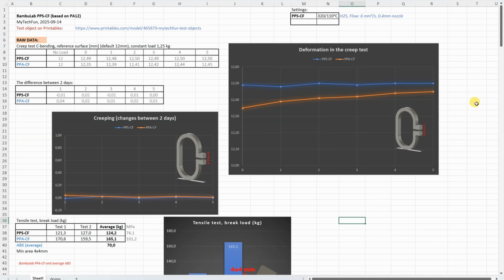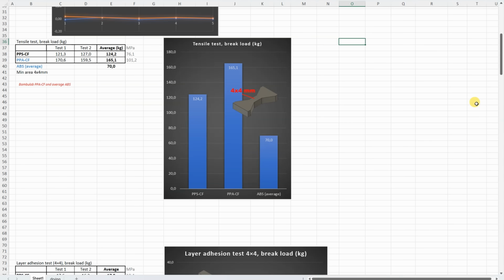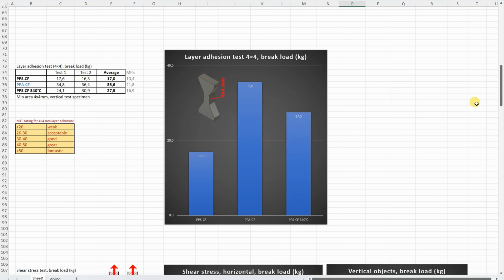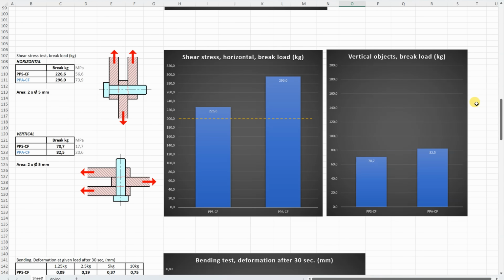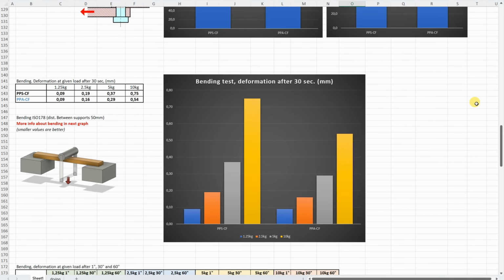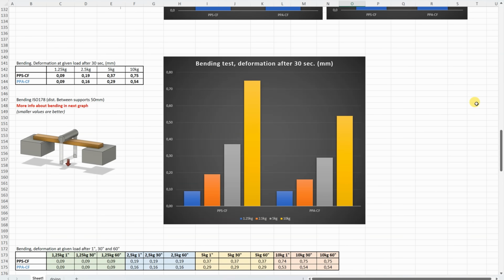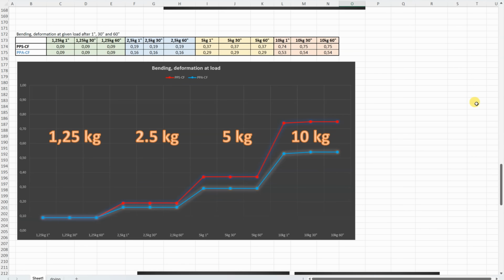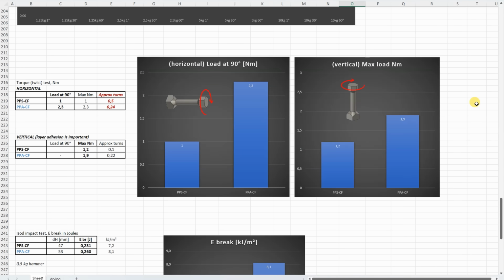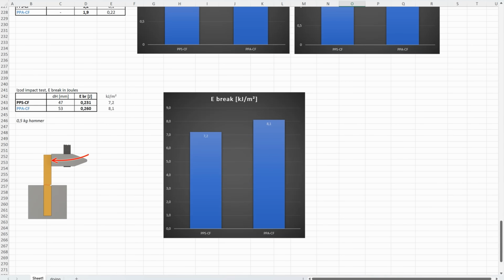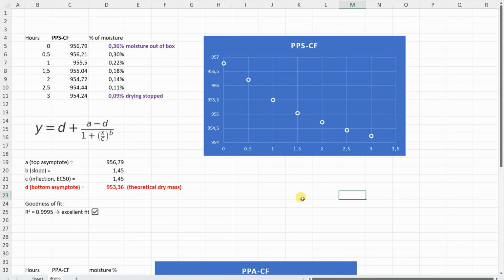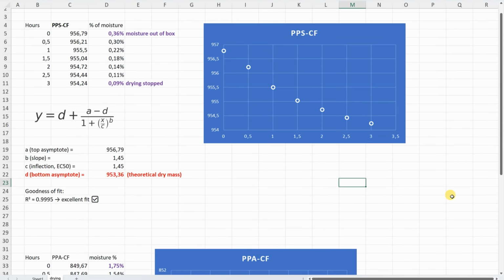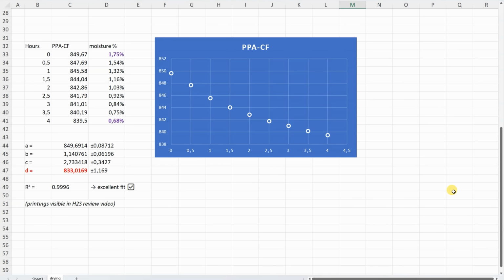Summary of all results in one place, and this one line will be added to the summary table for my Patreon supporters. Result for the shear test, bending test, deformation after 30 seconds, bending test, deformation after 1, 30 and 60 seconds, torsion test, impact test, and result of my drying for PPS-CF and PPA-CF.